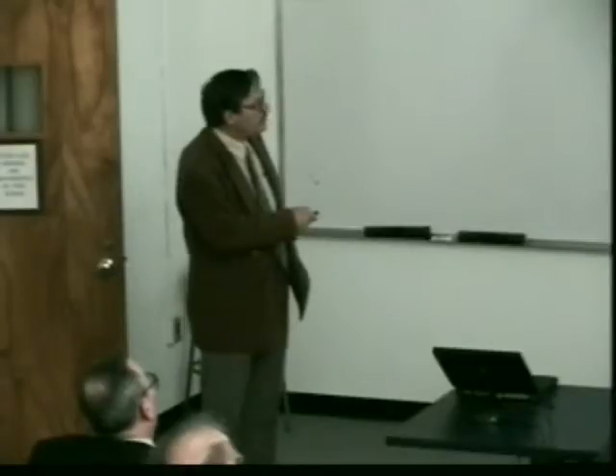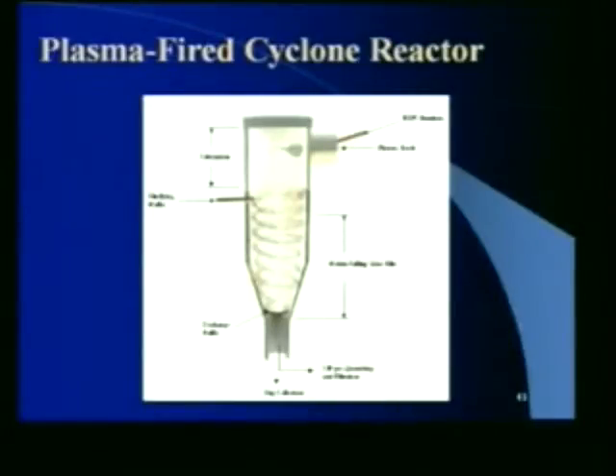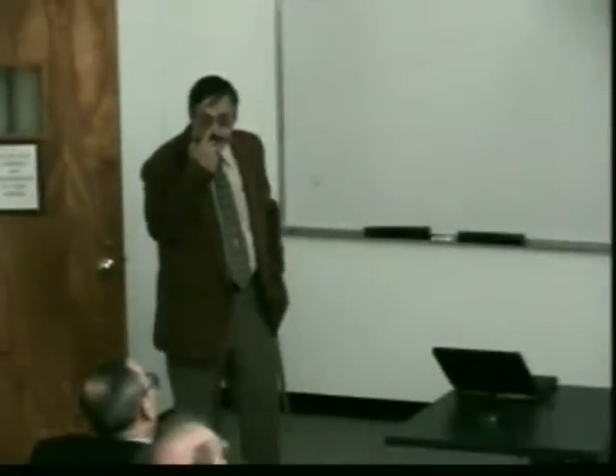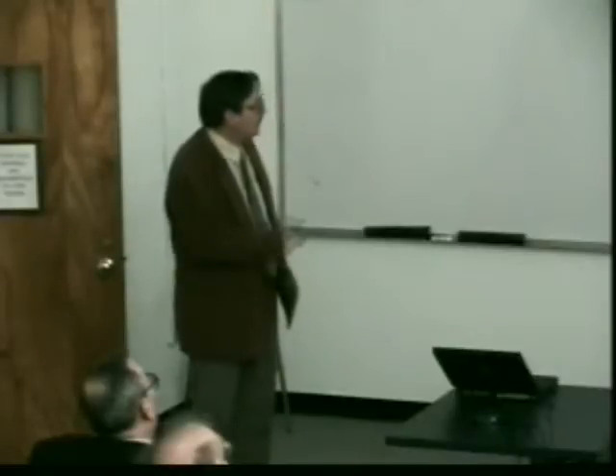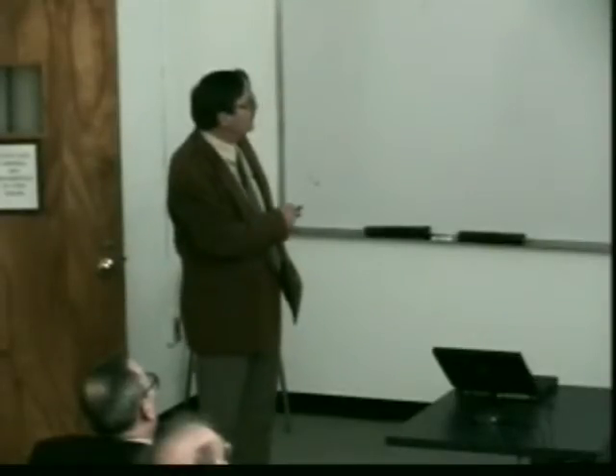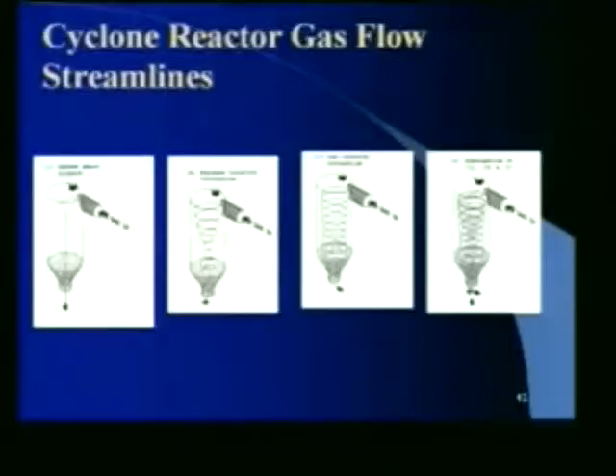This shows a discharge baffle where we put in some of these experiments to try to minimize the amount of material that might just short circuit through the bottom of this and go out of the system. We had built a plexiglass model of the same scale. But basically there's a possibility of a short circuit of a certain amount of material that just comes in and goes down the center. There's a maximum velocity streamline that goes near the wall, goes in, and then goes outside the wall. There's a low velocity streamline that follows the wall. If you combine all three, that's really the behavior. So high velocity here really forces things into the low velocity region at the wall, which then acts as a capture.